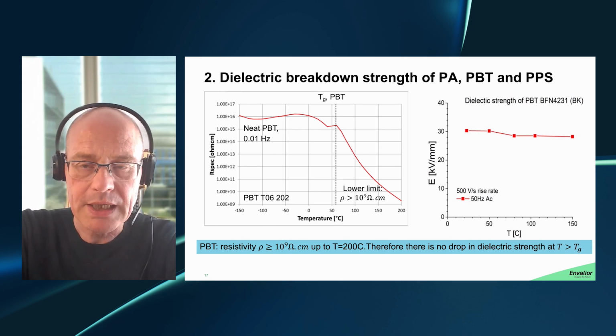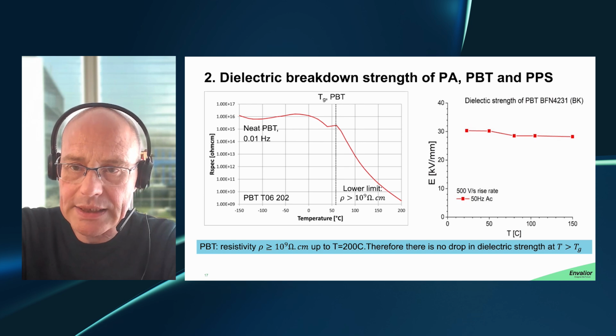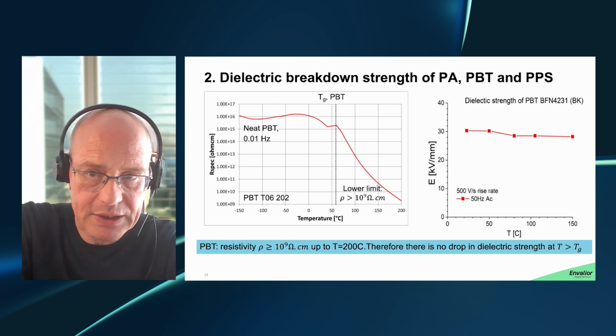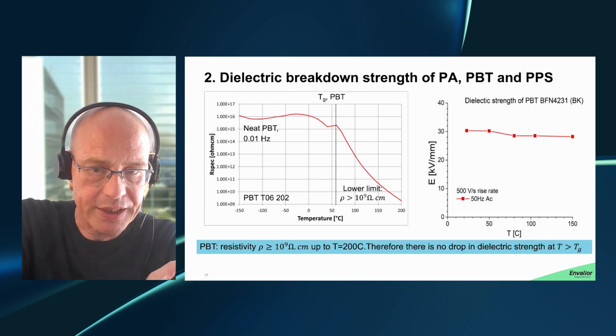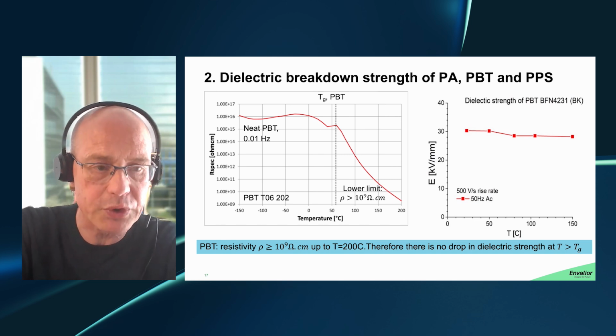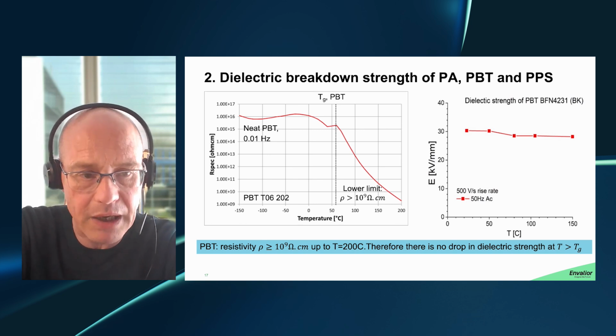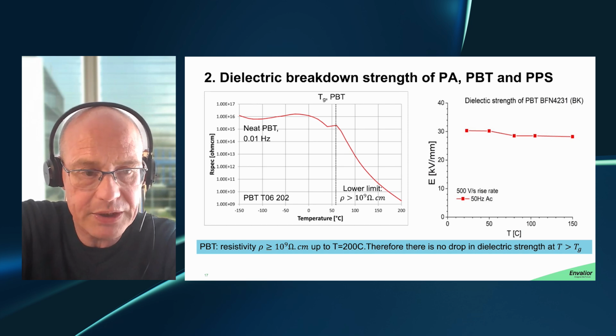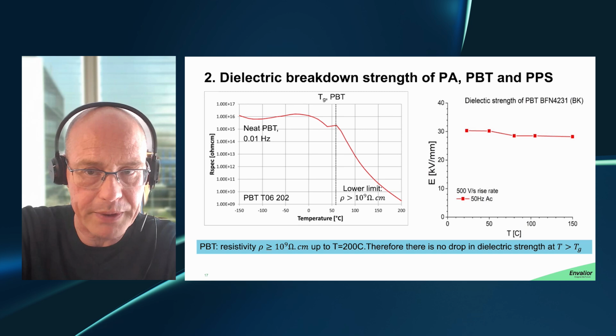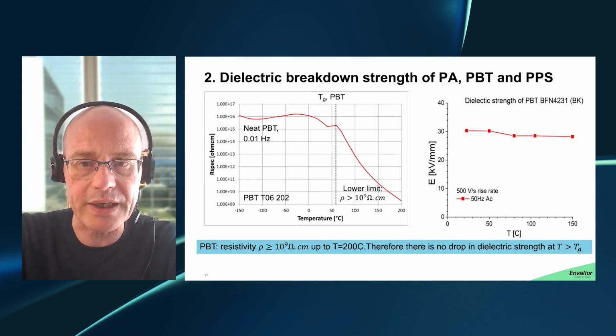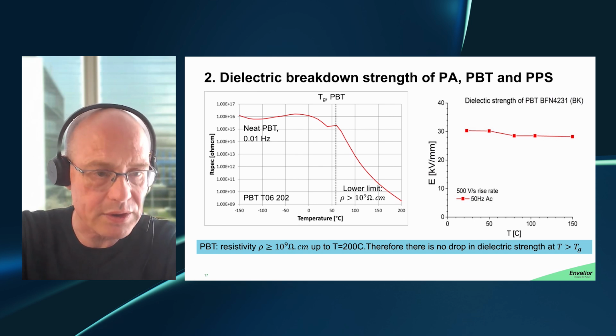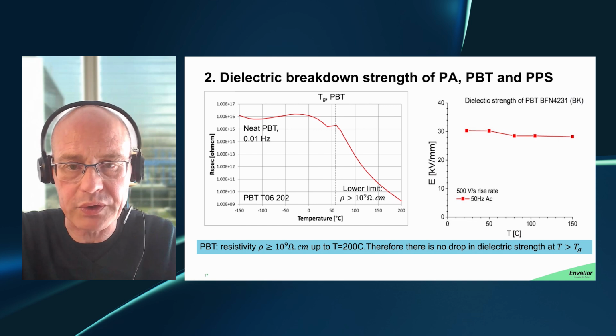This one is on PBT. On the left, you see the resistivity versus temperature of a PBT. And what you see is that, again, above the glass transition temperature there is a drop in resistivity because you're dealing now with a rubbery phase. Charge carriers can move through more easily, but in all cases, the resistivity is above this level of 10 to the power 9 ohms times centimeter. Therefore, there is no risk, as was shown with these thermal calculations, for a drop in breakdown strength, and that is indeed what is shown in the experimental data on the right. You see that the breakdown strength is guaranteed, is high at all temperatures that we looked at, well into the rubbery regime, so up to 150 degrees Celsius.